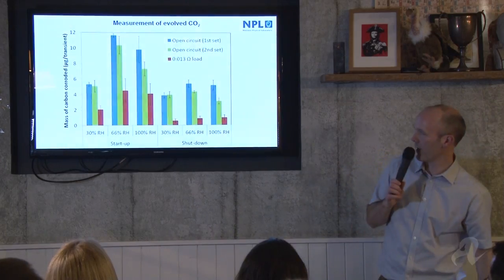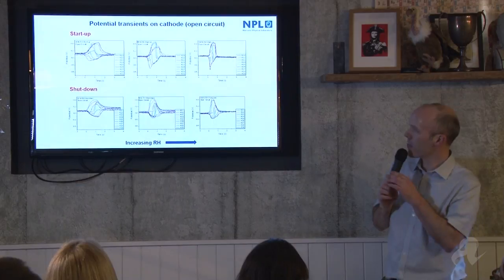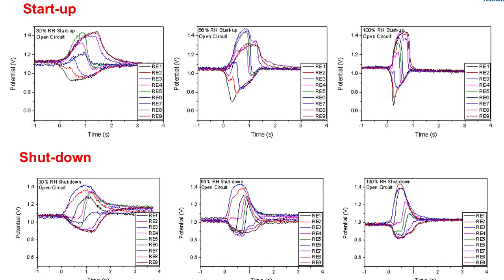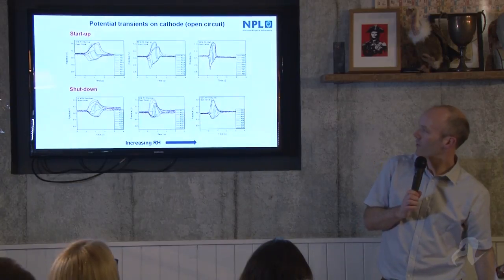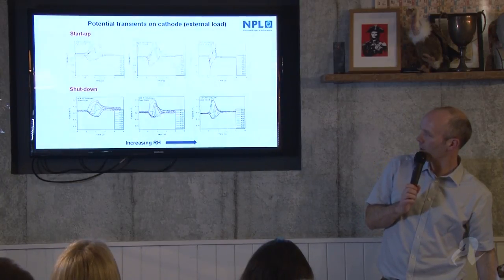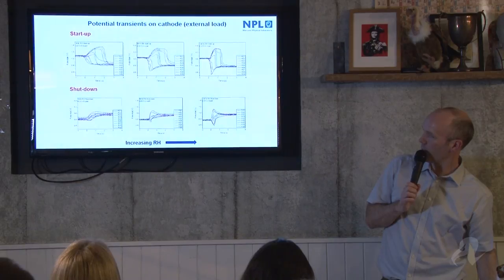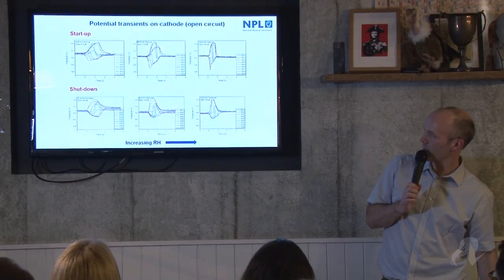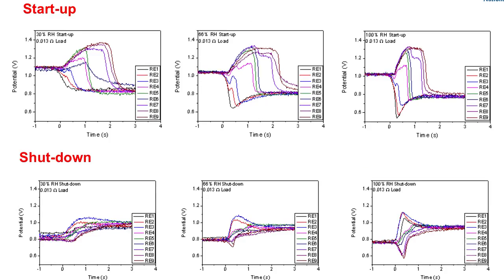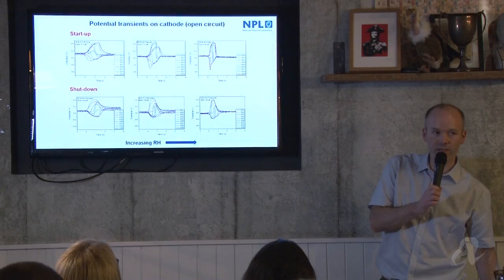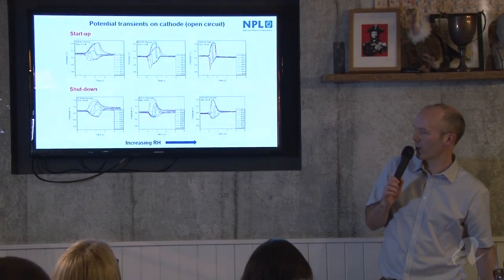So if we look at our potential measurements, I'll just flick between them. But these are our startup measurements at three different relative humidities in the cell. And these are our shutdown measurements of the nine reference electrodes. So if I flick between them, you can see that applying this small load really drops the potential significantly that you see on startup and particularly on shutdown. On shutdown, it nearly gets rid of it completely. So this is an effective way of solving the problem.